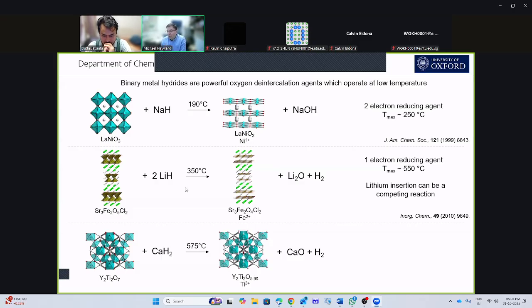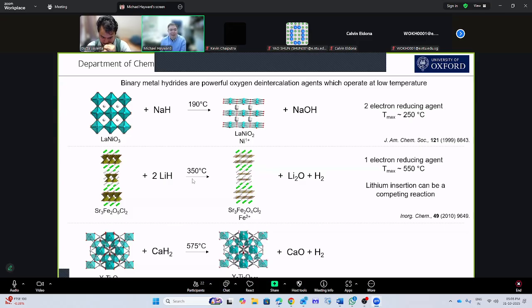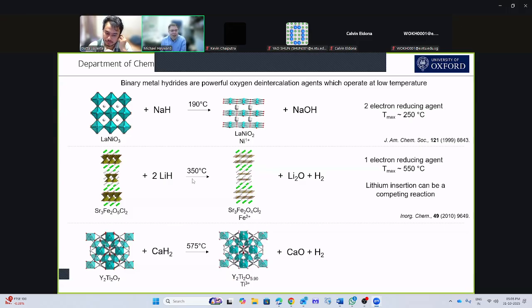If we look at lithium hydride to lithium oxide, lithium hydride has the rock salt structure. Lithium oxide is anti-fluorite. And so the lithium lattice needs to change quite a lot to go from hydride to oxide. So you have to add the energy to get that conversion. And calcium hydride is even worse because you look at calcium hydride and you assume it has the fluorite structure. It doesn't. It has something called the strontium iodide structure, which is very different from the rock salt structure of calcium oxide. So again, the activation energy to get the calcium hydride to go to calcium oxide is a little bit higher. So if you want to do a really low temperature reaction, sodium hydride is your best bet.